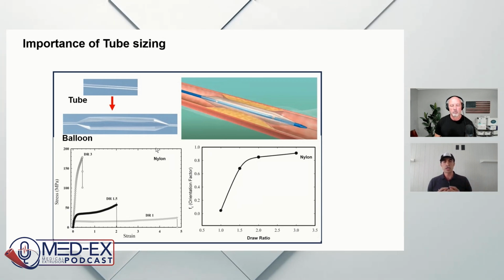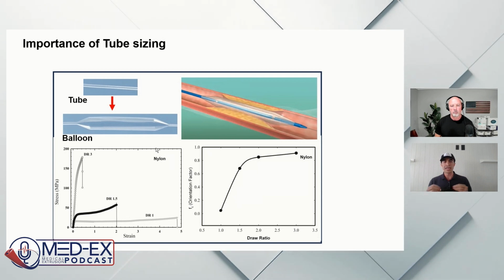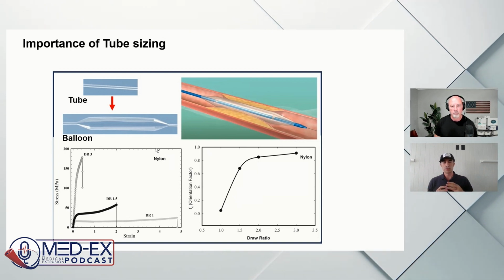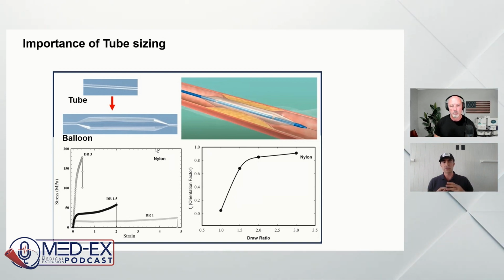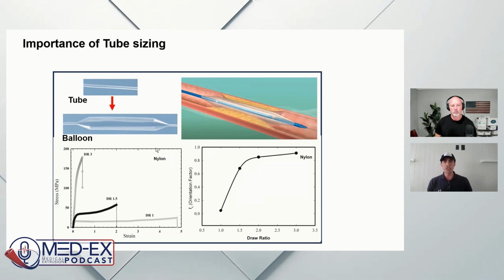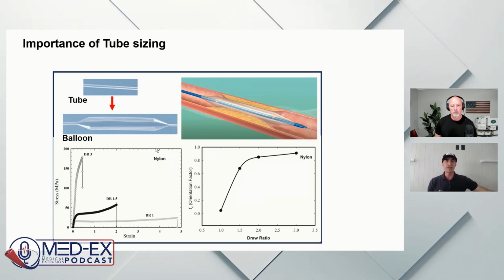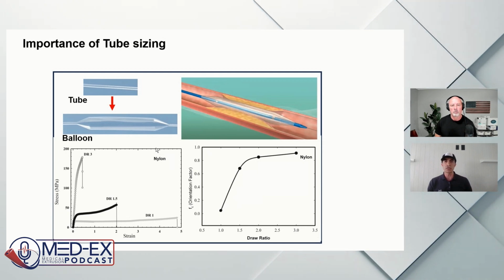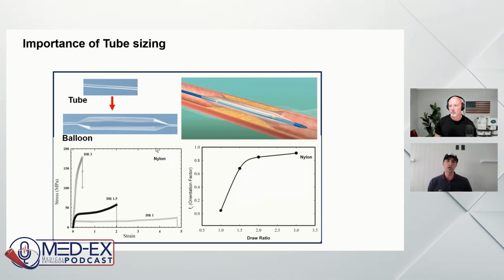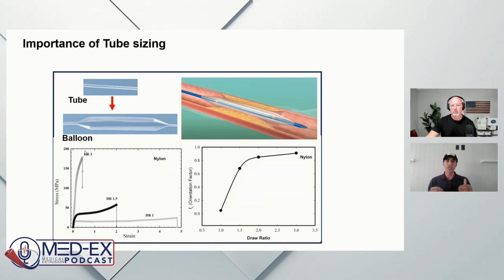Mm-hmm. That's where you stretch a tube in the axial and radial directions 3 to 5 times larger to get to the balloon. And the engineering or science behind that expansion ratio is in that graph that I presented here. That is a paper published in Polymer Processing that shows that after the expansion ratio of 3, the orientation function of the molecules reaches a plateau.